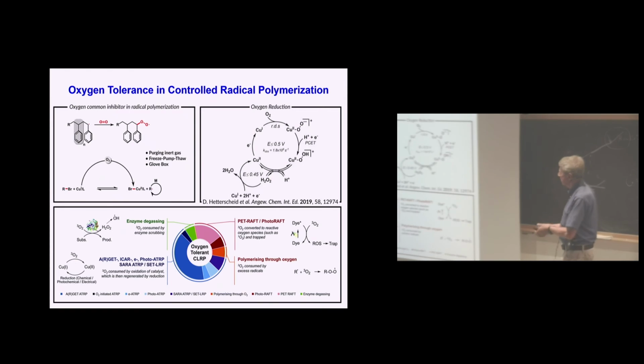Back to your question about oxygen. Oxygen is really an inhibitor which is extremely powerful because it forms peroxy radicals which react with monomer very, very slowly. So practically no polymerization. In the case of this atom transfer radical process with copper, it's even worse because these species are strongly reducing. So they will react with oxygen and oxidize themselves nearly instantaneously, these most reactive species. Sometimes you can use that process in order to produce electrochemically hydrogen peroxide. So use these copper complexes which work really very nicely.